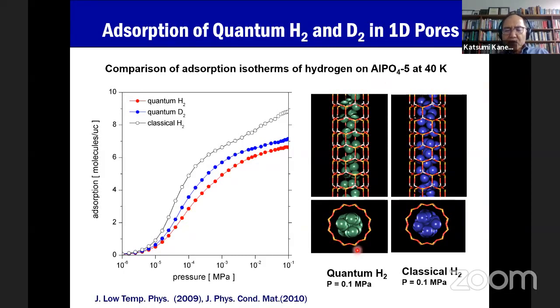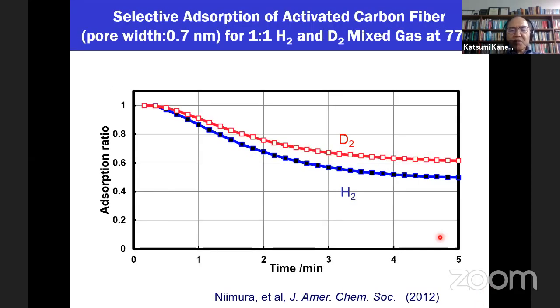In this case, on the left side, for the quantum hydrogen fluctuating system, you can see three hydrogen molecules adsorbed in this cross-sectional view. But for classical hydrogen, four. So one more molecule is adsorbed in the classical case, whereas at low temperature, when hydrogen is quantum, less hydrogen is adsorbed. Very unique adsorption behaviors are observed for hydrogen isotopes. Even for mixed gas, hydrogen and deuterium, differential adsorption is observed for ordinary activated carbon fibers.